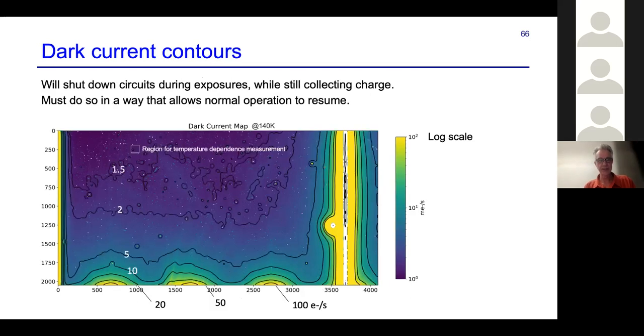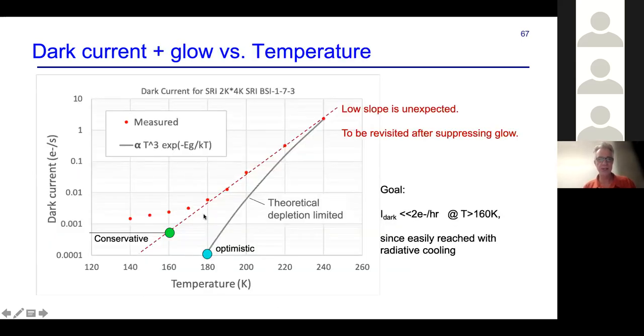But how well are we doing? Well, not terribly, but not as well as we want to be. So if I pick that white box up here and plot the dark current versus temperature, I get the red dots here. And you can see that the dark current is coming down. Somewhat perplexingly, it's not following the theoretical curve here in gray. So I would describe a point on the theoretical curve as being somewhat optimistic at this point. But if we were to fit a straight line to the top of the curve and extrapolate downwards, that might be a worst case scenario for what we'll get when we suppress the glow. My expectation is that real life will fall somewhere between the green and the blue.